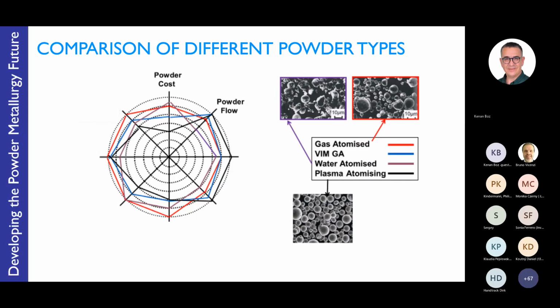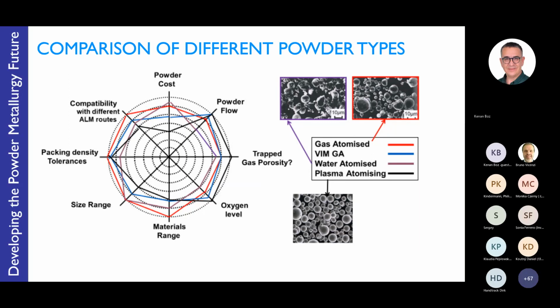So of course we have to consider cost of the process. Inert gas atomizing is generally the lower cost, higher throughput in terms of volume and flexibility. Powder flow is an important characteristic, especially for layer-based systems like powder bed fusion and electron beam. Entrapped gas porosity, especially for coarser powders, and the oxygen level, and no doubt there is an advantage for vacuum melting as well as plasma atomizing.